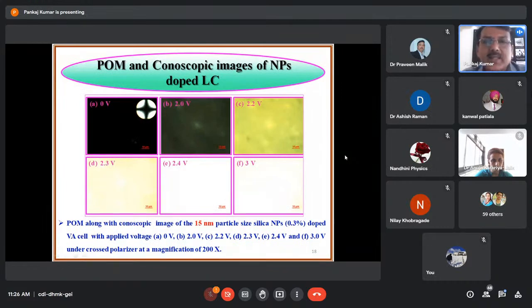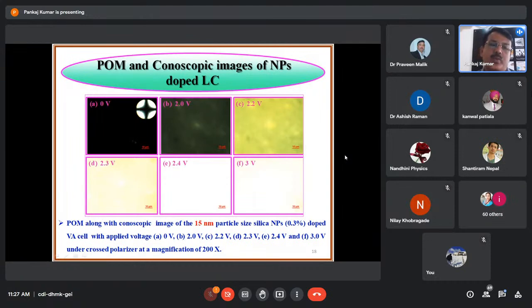Here you can see under the applied voltage, at 0 volt it is perfectly dark, and at 2 volt you can see the liquid crystal molecules start to change, at 2 volt, 2.2 volt, 2.3 volt, 2.4 volt and 3 volt. At 2.3 volt the perfectly bright state is there. So POM along with conoscopic image of the 15 nanometer particle size at 0.3% doped VA LC, with applied voltage 0 volt, 2 volt, 2.2 up to 3 volt under crossed polarizers, and the magnification was 200x.